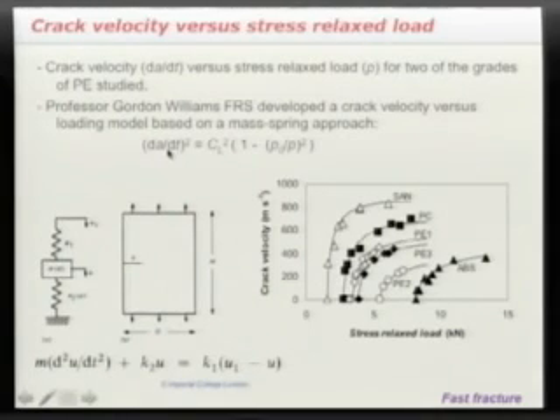And when you solve it, then you get a relationship between crack velocity and load, which has this characteristic form with a threshold load and also a limiting crack velocity, which is what we observed experimentally. And so we could explain these threshold and crack velocity processes in terms of this model, which was useful.